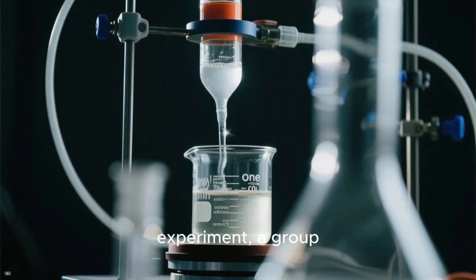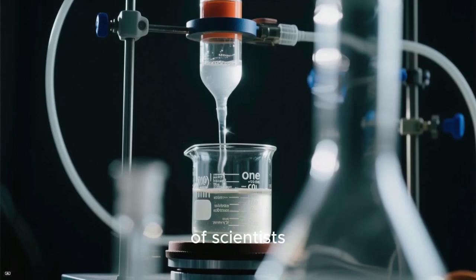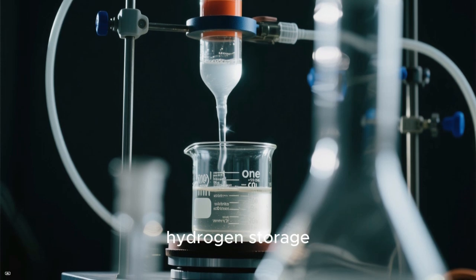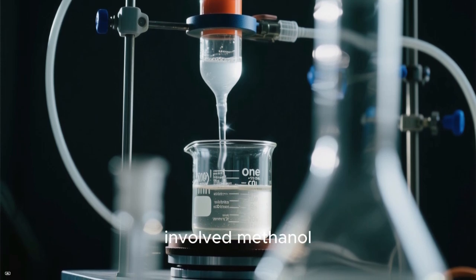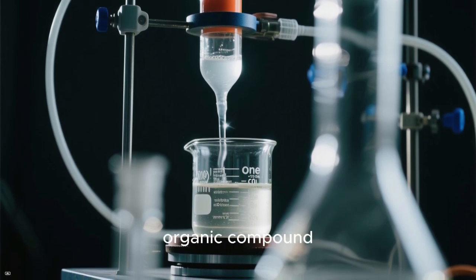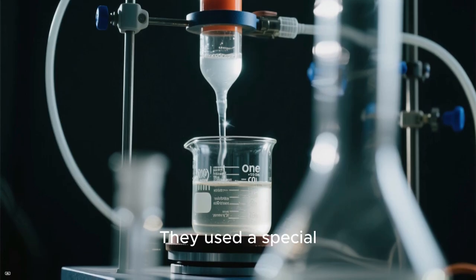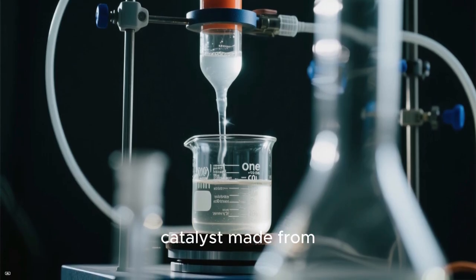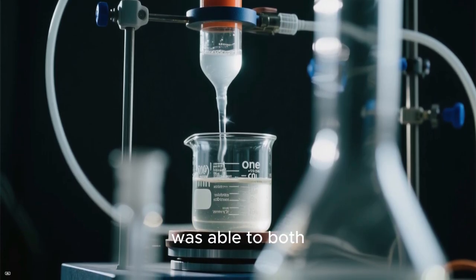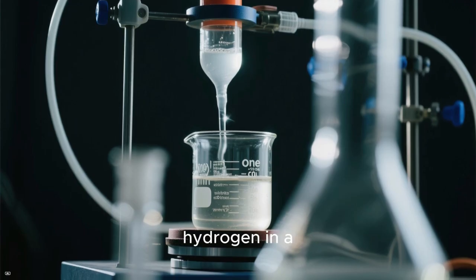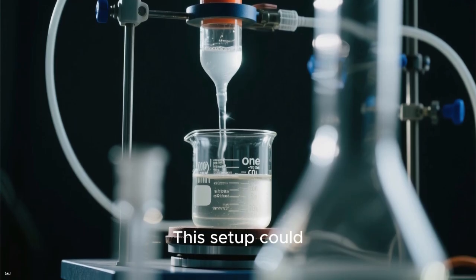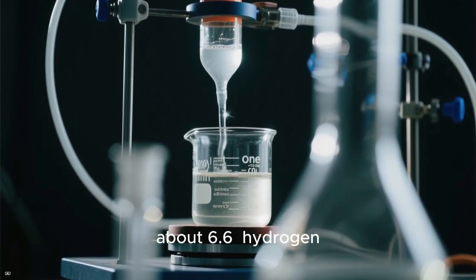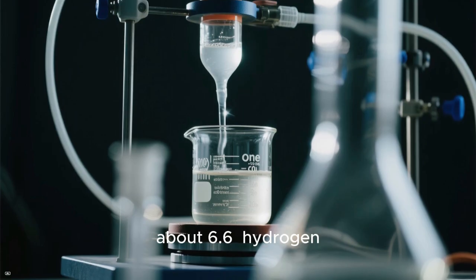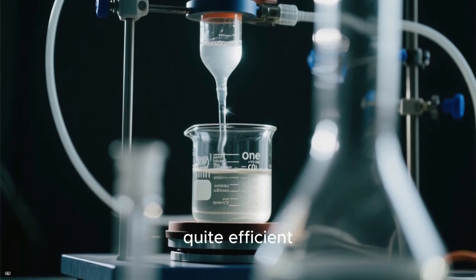In a different experiment, a group of scientists tested a one-pot hydrogen storage method that involved methanol and a type of organic compound called 1,2-diamine. They used a special catalyst made from ruthenium, and it was able to both store and release hydrogen in a reversible way. This setup could potentially hold about 6.6% hydrogen by weight, which is quite efficient.